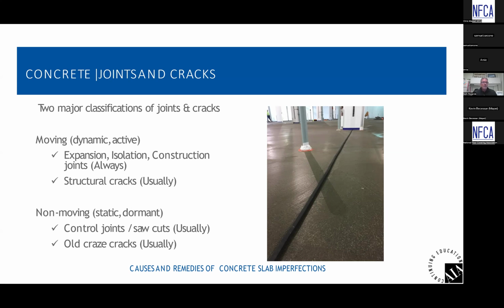Some of the non-moving ones that we see out there, also referred to as static or dormant joints or cracks: number one, control joints, or the saw cuts. We'll address this. And sometimes you see crazing cracks, also called old craze cracks. The surface of the concrete dries out and it can create a crack pattern that looks like a map. But that happens during the drying process of the first couple of days and is typically not a moving crack by any means.